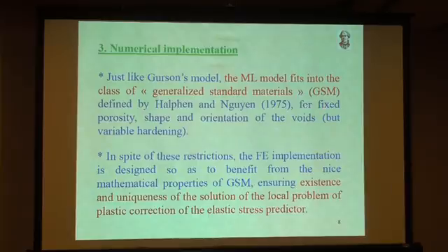But in order to fit the model into the class, you have to assume that the porosity and the shape and orientation of the voids are fixed. So this seems completely stupid and unrealistic, but it's not so stupid, because it's possible to design a finite element implementation so as to benefit from the nice mathematical properties of a generalized standard material.